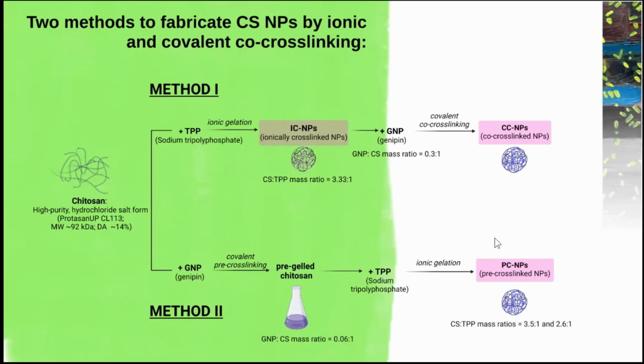And method 2 is an inverted version, and it starts by a covalent pre-cross-linking of Chitosan with genipin to obtain a pre-gel Chitosan that is further ionically cross-linked with TPP to render the pre-cross-linked nanoparticles. And this is a novel method that we have developed in our lab in Münster.